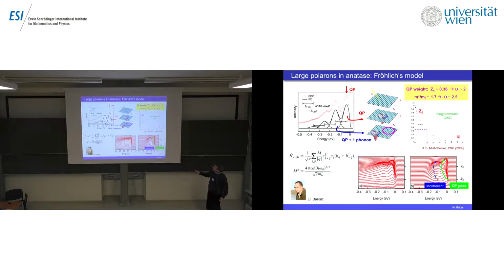Now, the spectral function, as you know, can be modeled in the Fröhlich model. At least the first satellite can be modeled. This has been calculated also by Barisic. So you see the quasi-particle and the first satellite. So the quasi-particle corresponds to the fact that we remove an electron and we leave just the quasi-particle itself. The first satellite would be the final state with the quasi-particle plus one phonon in the system, and so on and so forth. So this can be modeled, and it's pretty much what we observe in the spectrum.